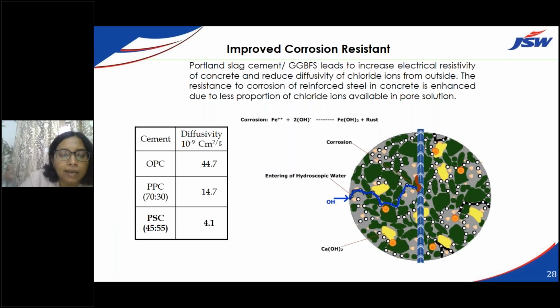So this is again a diffusivity slide, a very important slide. Everybody must have seen this, many people. So OPC diffusivity is 44.7 into 10 to the power minus 9 centimeters square per second. Basically, there are a lot of pores and voids and channels in the system, and when you are using OPC, there is a linkage which is happening in this. And when PPC cement is used, then the diffusivity reduces to 14.7. However, there is a drastic drop in diffusivity if Portland slag cement is used. Portland slag cement, which is the replacement level is 55% here. The diffusivity level is 4.1 into 10 to the power minus 9 centimeters square per second.